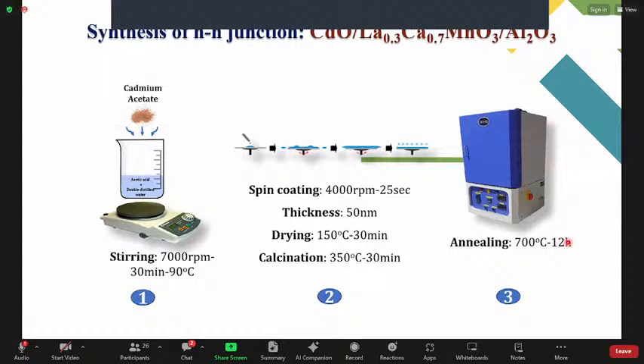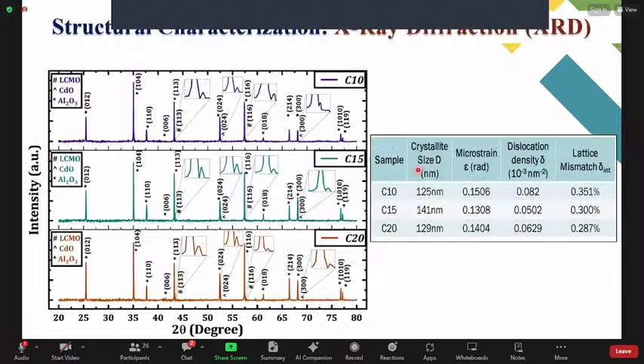Now on this LCMO layer, we will deposit another CDO layer in the same manner. Just we will use the cadmium acetate as the precursor. This is the XRD structural characterization. From XRD, we can see that the crystallite size is first increasing for C15 and then decreasing for C20. Now the microstrain values are also given here, dislocation density, and all these parameters have been calculated from the XRD only.